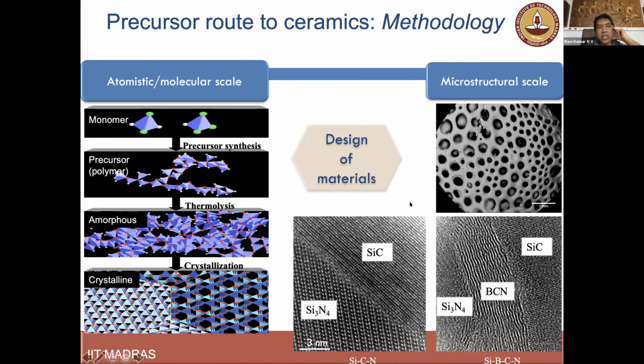On the left-hand side, I show you a schematic of how we make these materials. We produce precursors based on the kind of ceramic material that we would like to use for a certain application. Starting with monomer units, we make precursors, and then subsequently subject them to solid state thermolysis to obtain amorphous ceramics, and then depending on requirements, we heat treat them to obtain highly stable crystalline ceramics, thermodynamically stable crystalline ceramics.